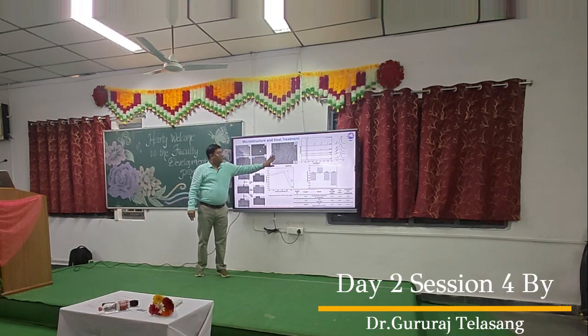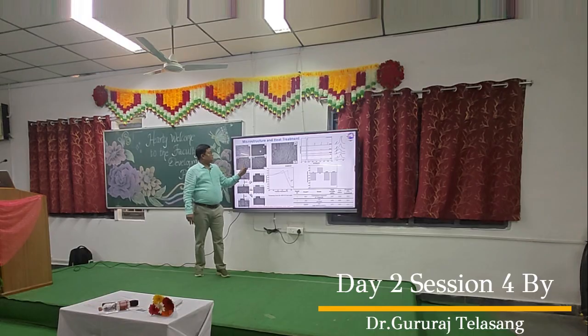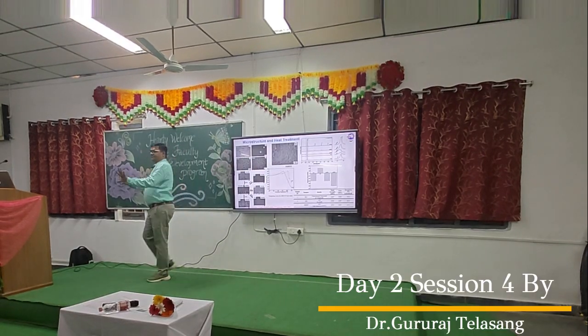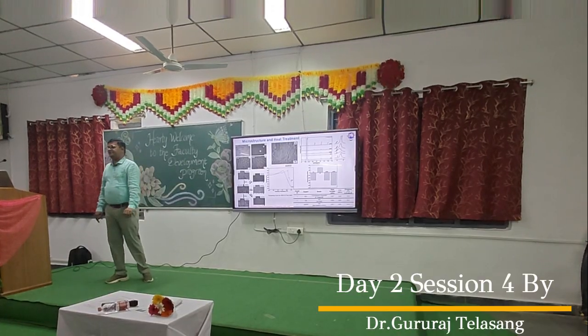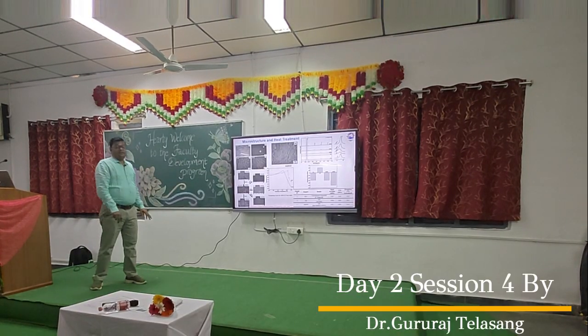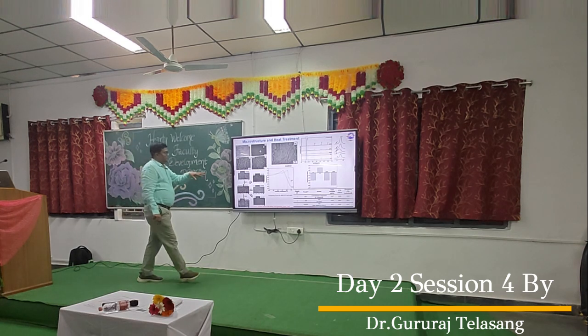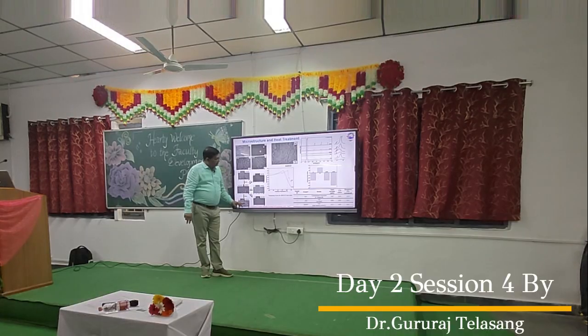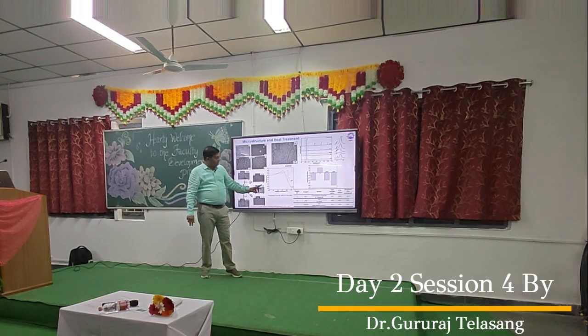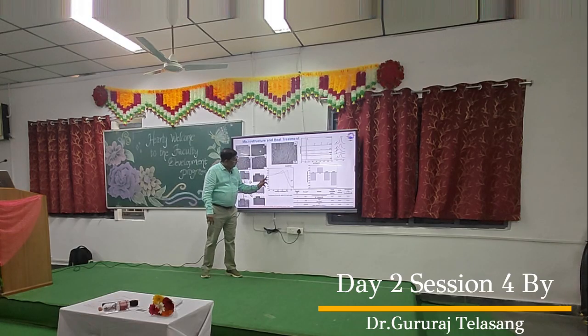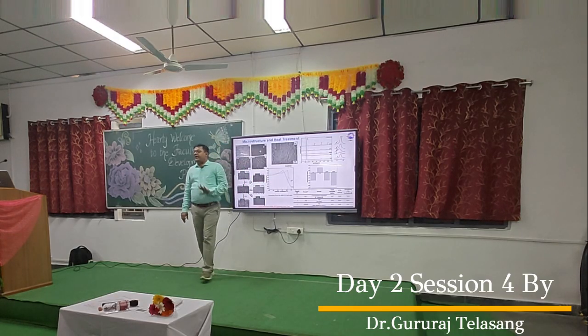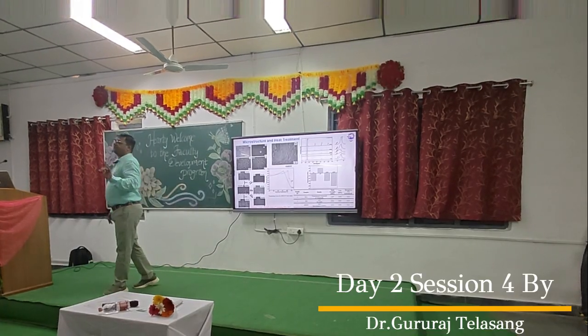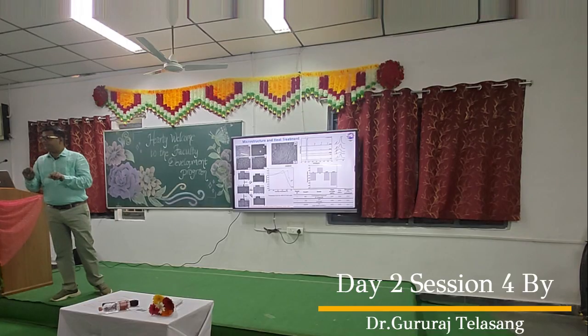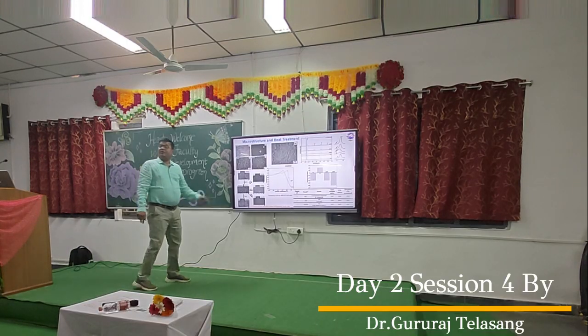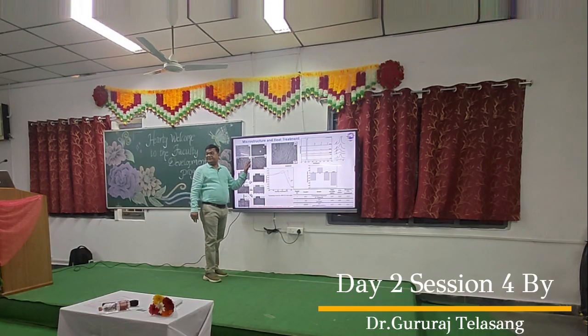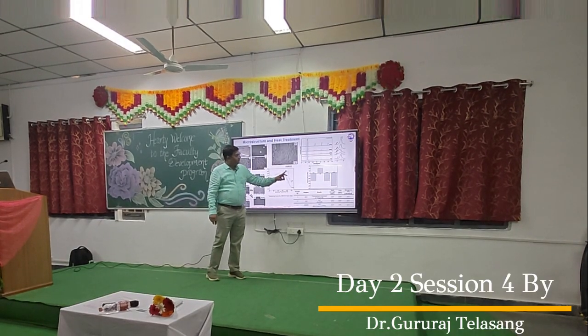This is the microstructure we achieved after heat treatment up to 650. From this to this, diffused, all gone, and the bright spots are carbide precipitates. That's what we need. Now will it end here? No. After that we check what has happened. So this is the hardness we measure for each microstructure after the exposing temperature. You can see there is a temperature, there is a hardness. We plot that, it's called the tempering curve. Any material you buy from the market, they have to give this tempering curve data sheet. So we generated the tempering curve for our AM sample because our microstructure is different. Can you see the shift?